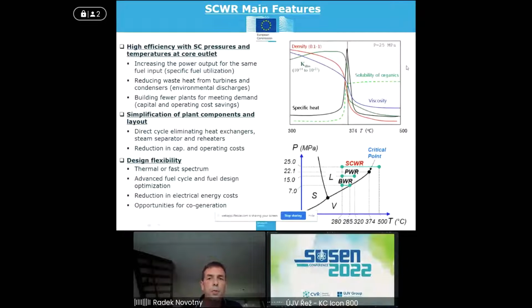But if we look a little bit at the problems, the big problem is the change of water properties crossing the supercritical point. You can see most of the physicochemical properties change significantly when we go from subcritical to supercritical water. I would specifically mention specific heat having a peak around the critical point, and this is causing an effect called heat transfer deterioration, with hotspots along the peak, leading to big problems for materials experts and making it a critical part of the development of materials.